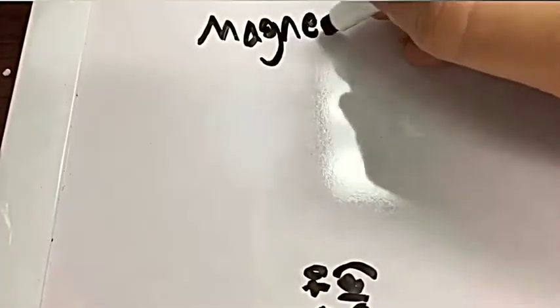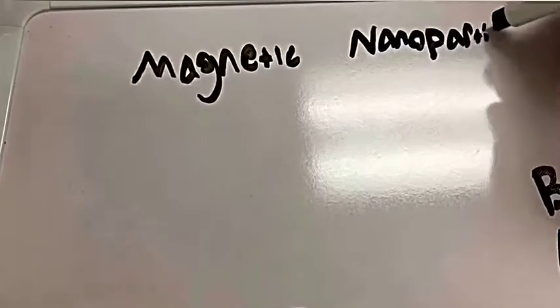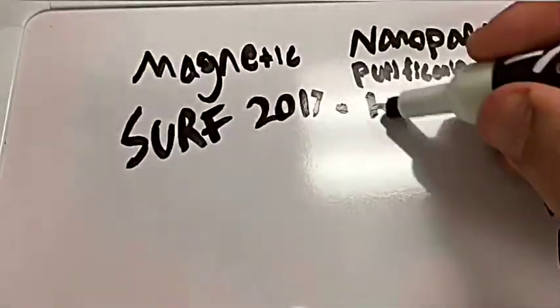So far, our procedure has shown promising organic content from TGA, reducing the percent organic content from 99.9% to about 25 to 50%. In the future, we hope to show consistency of this process across different batches, in inter- and intra-batch reproducibility, for an easy method of cleaning nanoparticles for further applications and functionalization.